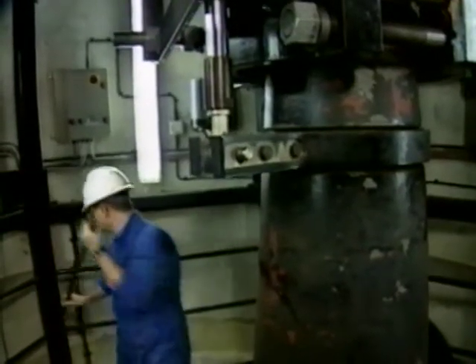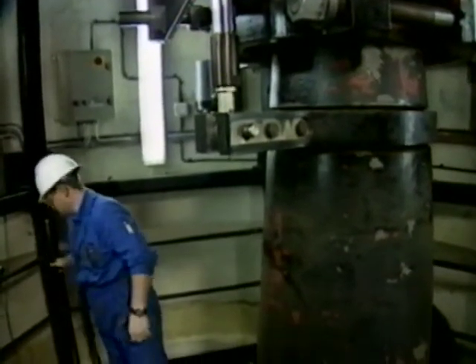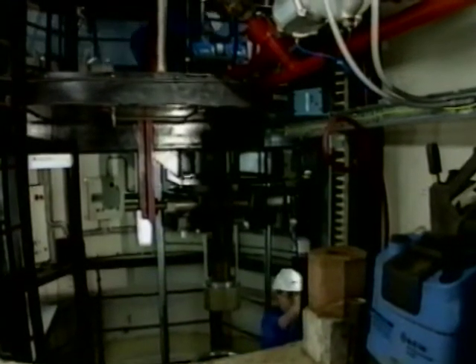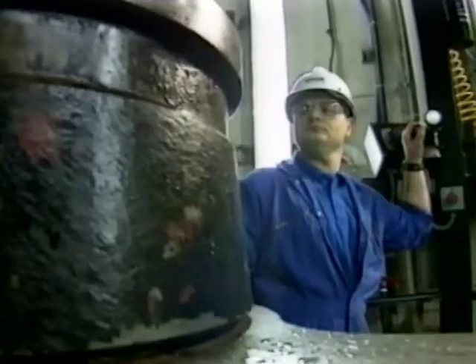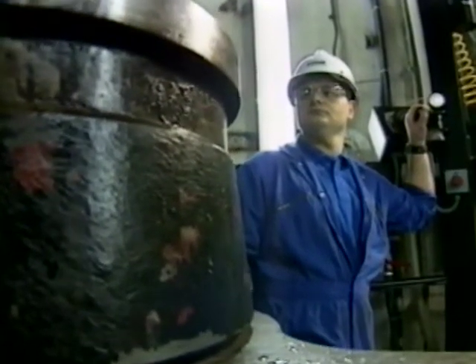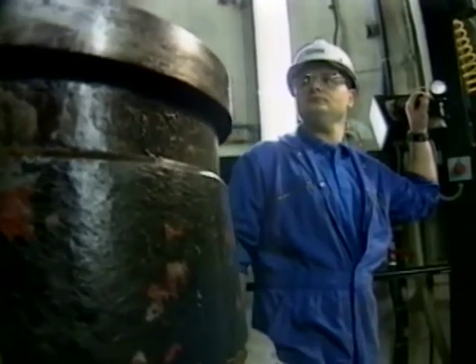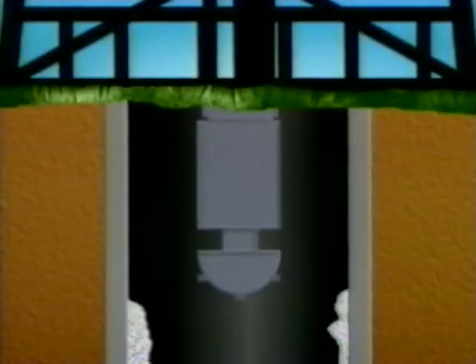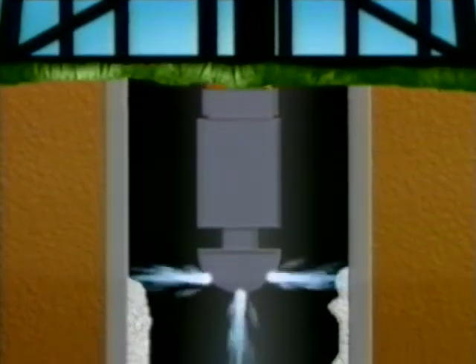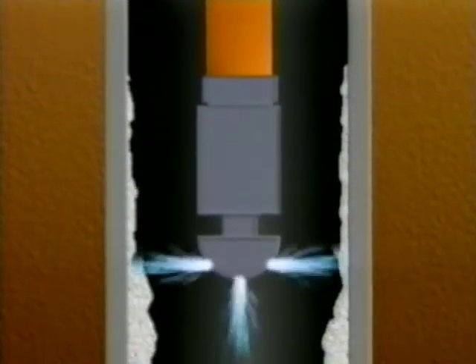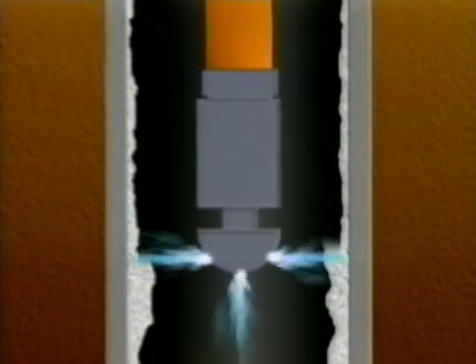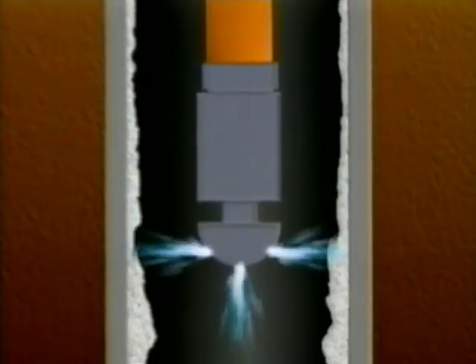Our first step was to undertake an in-depth study of jetting performance. The most critical finding was that the performance of a jet under downhole conditions was significantly different to that encountered on the surface. In surface conditions, without back pressure, small bubbles form in the jet and collapse on the target with a large erosive effect. This process is known as cavitation.